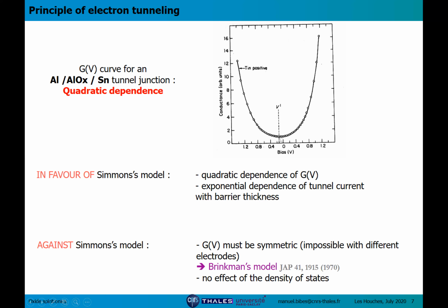And here I must say that this shift comes from the fact that the junction is not symmetric. So we have two different metals, and so they have two different work functions. And so the tunnel barrier is not rectangular, as I showed in the very simple example a couple of slides ago, but it's actually trapezoidal, okay? And this causes a shift of the minimum of the conductance.